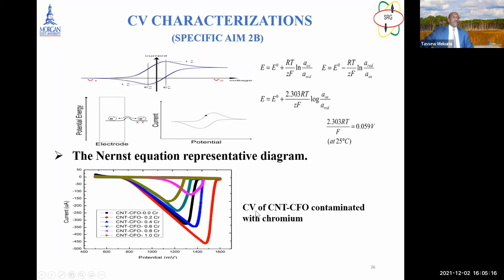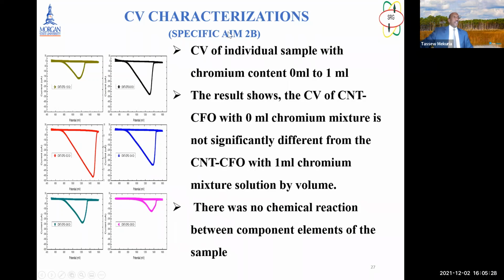As you can see here, these are not significant. The cyclic voltammograms of CNT and the CFO contaminated with chromium did not show significant difference. So we tried to see the individual peaks, and in each of them the differences are not significant, so we come to the conclusion that there was no chemical reaction between the components of the sample. The samples are simply hooked together, and the carbon nanotubes are used as a tube to transport the CFO materials, and the chromium is just dispersed over them. And that is very good for VSM and also for EXAFS and also for SANS.